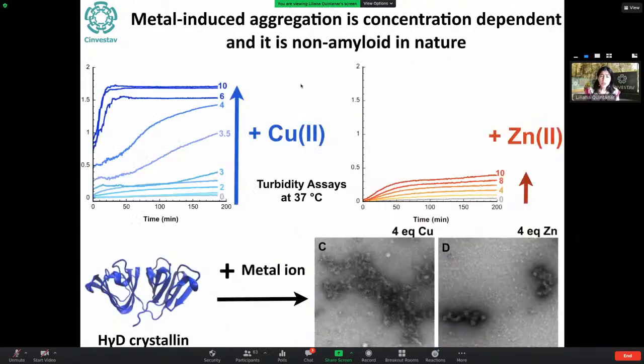What we did is, well, I went to his lab for a sabbatical. We took this protein, human gamma D crystallin, and we confronted it with different metal ions. And we found that copper and zinc can induce the non-amyloid aggregation of this protein. And of course, the more metal ion we add, the more aggregation we see. These are turbidity assays. The nature of the aggregates is non-amyloid. And as you can see, the effect of copper is much more drastic than zinc. We have some stories on zinc and other metal ions, but I'm going to tell you today about copper.